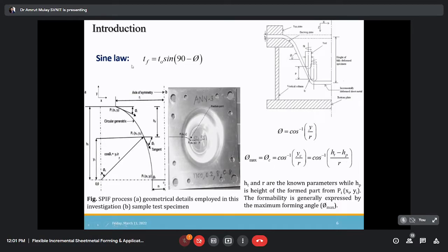It means that when you form some component, the theoretical relation says that TF is the final sheet thickness. You can see here at the bottom, the final sheet thickness depends on the initial sheet thickness multiplied by sine 90 minus phi. Phi is the forming angle. So the forming angle you know, the phi angle you know, the initial sheet thickness you know. Suppose you are preparing some component, the initial sheet thickness is 1 mm or 1.2 mm, that you know. Phi also you know, so T final can be calculated.